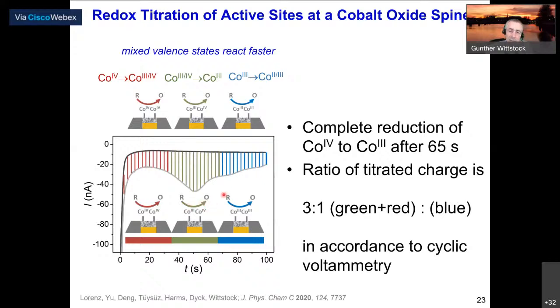So a large charge for that, and we can calculate the ratio of these and get about a ratio of 3:1 for the green and the red system, with respect to the blue, which suggests that we see here the conversion for the cobalt-4 species to the cobalt-3 species, and then furthermore to a mixed valence state where some of the cobalt is in the cobalt-2 state. Now the question is, of course, why do we see different reaction rates? And one assumption is that the mixed valence state has a particularly high kinetics for the reaction with the redox mediator, which may also have something to do with the conductivity of that material in that state.